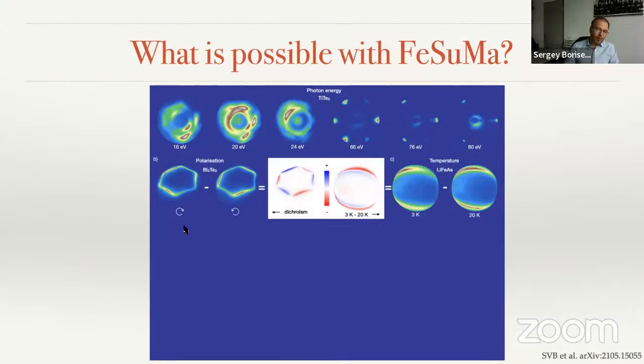Since this is a conference about topology, the meaning of this for topological materials is also very high, because, for instance, you are interested in a very quick estimate of the spin texture of the topological surface state. This experiment lasted in total 1 minute, 30 seconds for this map, 30 seconds for the other one, and then you see the circular dichroism, which is very clear here.